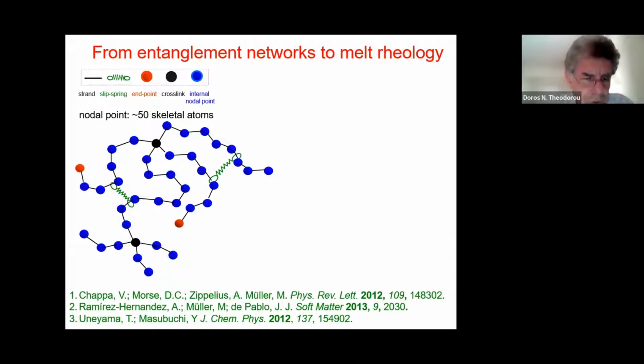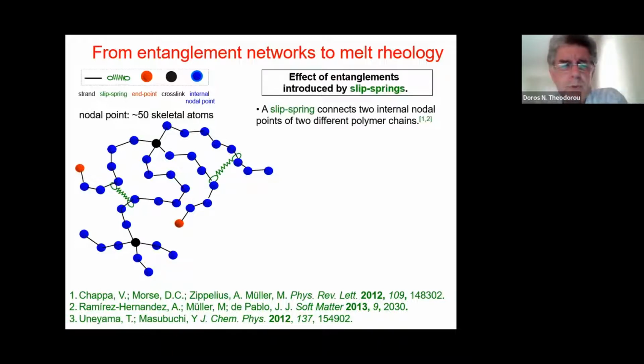We employ a coarse-grained representation for the polymer, where each chain is represented now as a sequence of beads and springs. And each bead stands for something like 50 skeletal atoms. It is quite an aggressive coarse graining that we're introducing here. The beads are connected to each other through springs, which represent the entropic elasticity of these strands. And in addition, to represent entanglements, we introduce what is called slip springs. This you will find in a number of relatively recent articles in the literature.